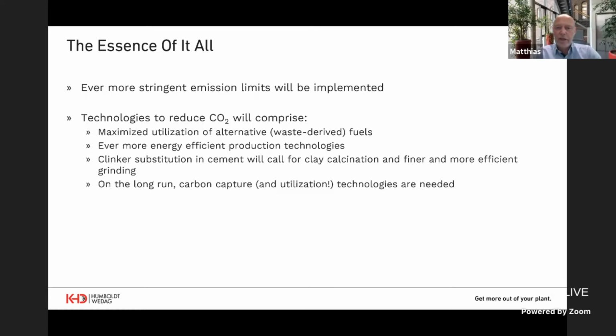Ever more energy efficient production technologies have to be applied. Clinker substitution in cement will call for clay calcination, but it will also call for changes in the grinding technologies because they need to be ever more efficient, and there will also be a demand for ever finer cement grinding to compensate for a lower clinker portion in the cement. And in the long run, and we talk about being commercially available by the end of this decade at the latest, carbon capture technologies are needed. And I put in brackets here with an exclamation mark, and utilization, because if there is no utilization path, capturing all that carbon wouldn't make much sense. So this is the longer ranging objective for us as the cement industry.